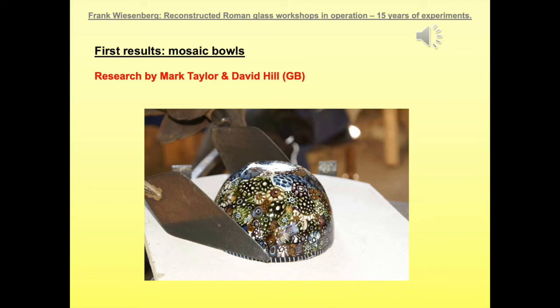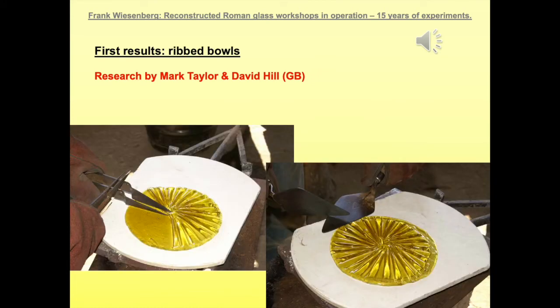After being annealed, so after a day or night of annealing, it's taken from the annealing oven. The rest of the mold material can be scraped off, and the inside of this mosaic bowl can be ground and polished afterwards. So this might explain the manufacturing marks and polishing and grinding marks which can be noticed on the Roman originals. According to Mark Taylor and David Hill, a quite similar technique can be used for manufacturing of rib bowls.